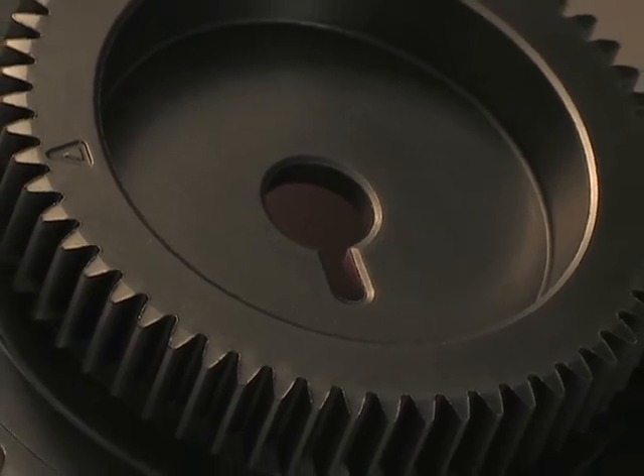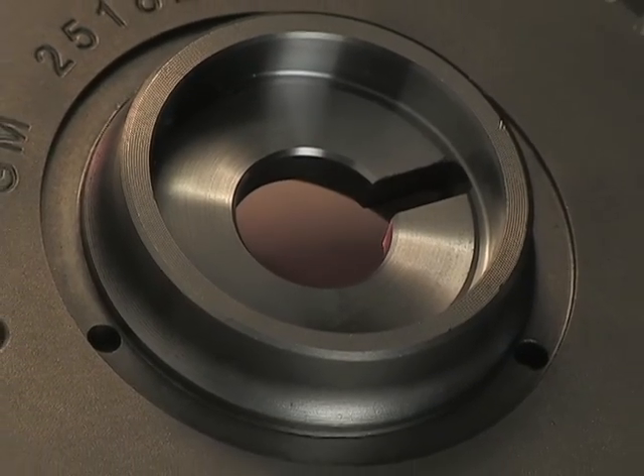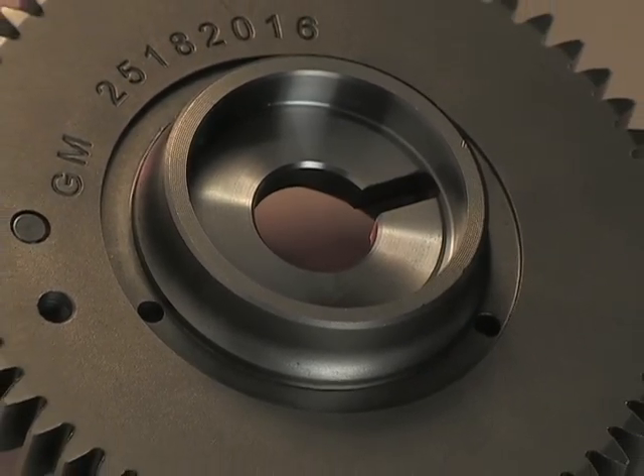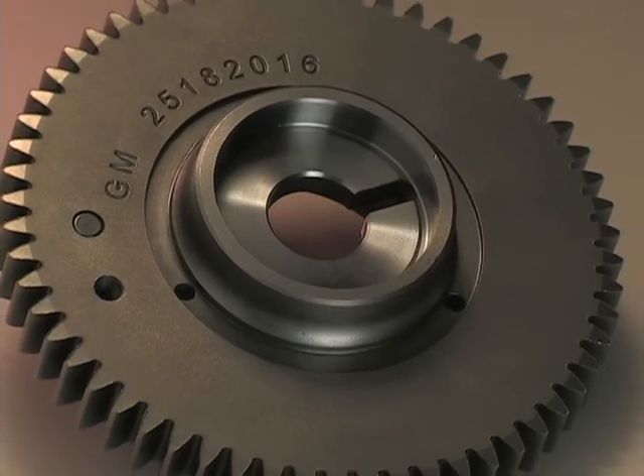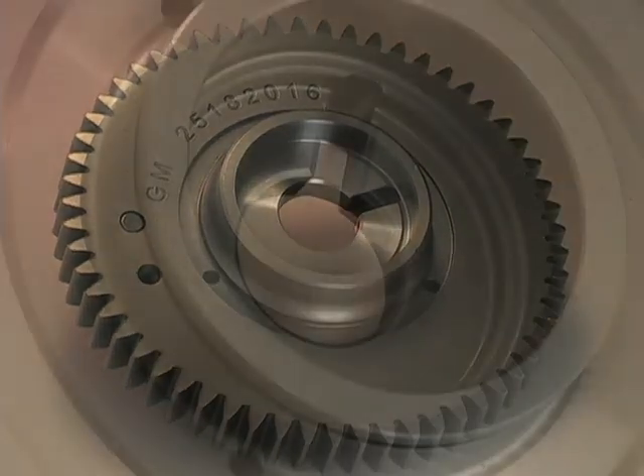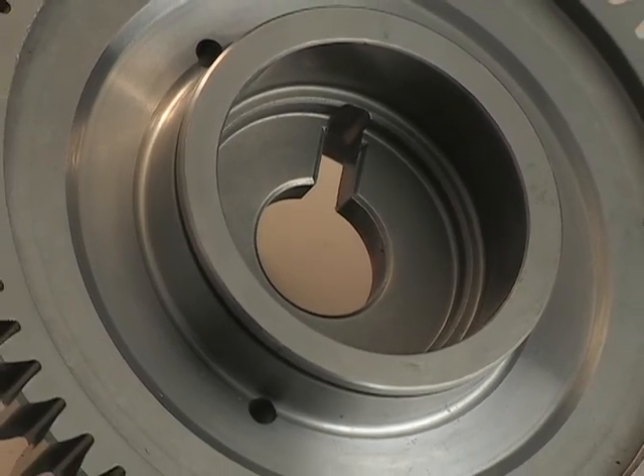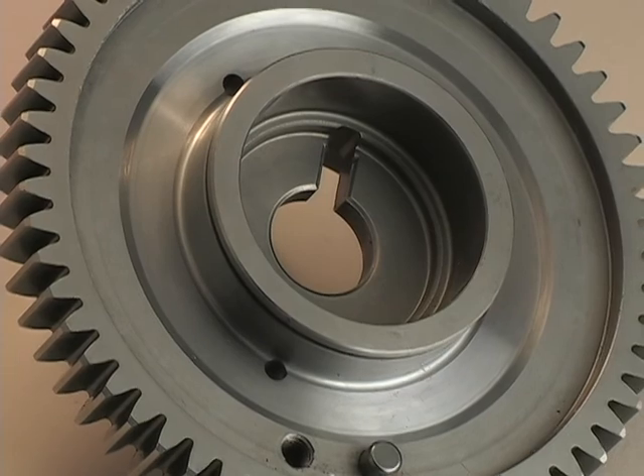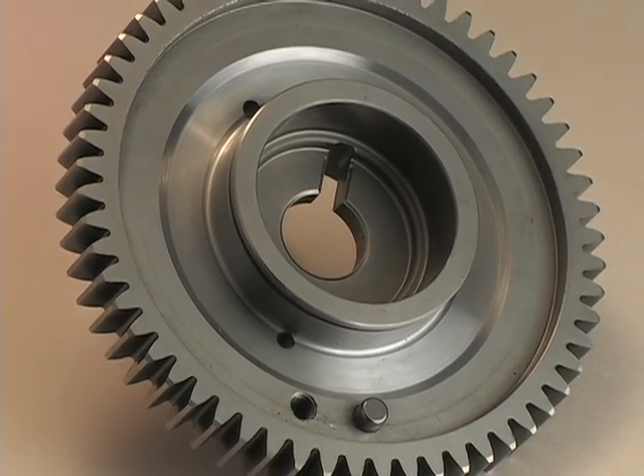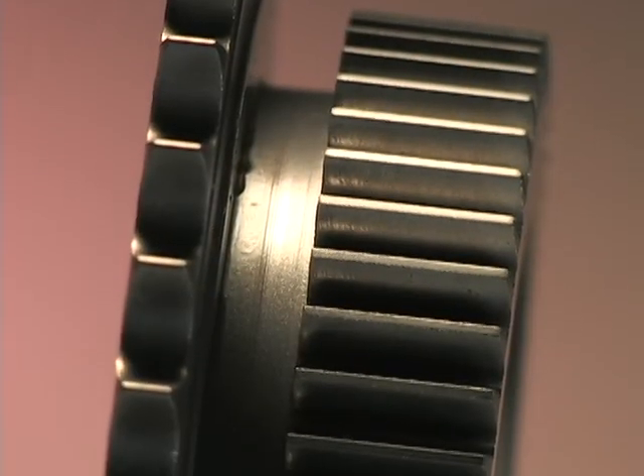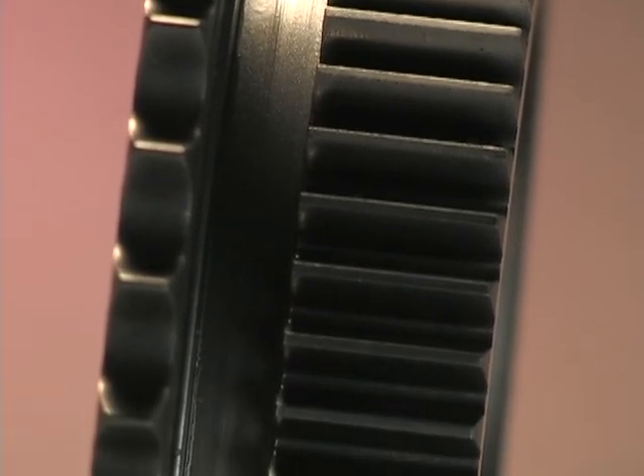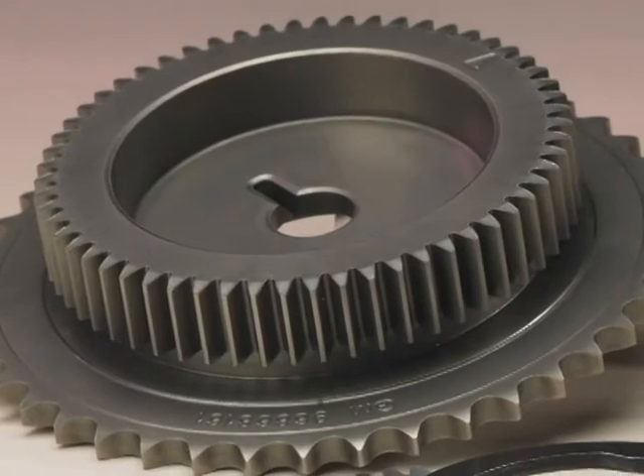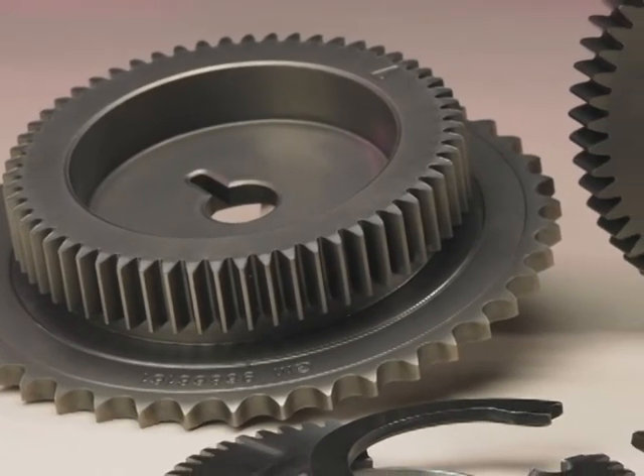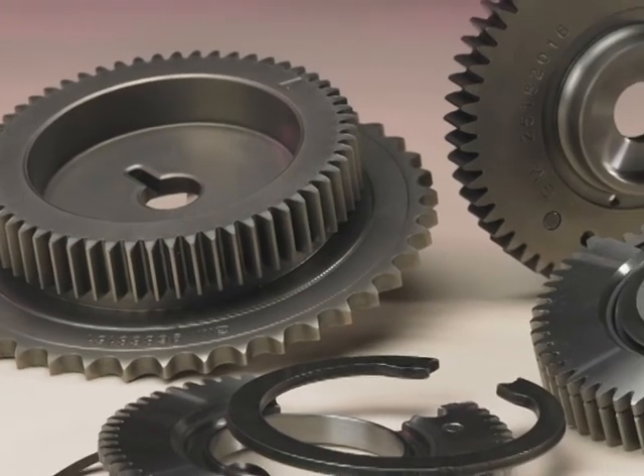noise, vibration, and harshness. Warm compacted to a 7.2 grams per cubic centimeter minimum density on the teeth, the PM steel gears have an ultimate tensile strength of 196,000 psi, typical yield strength of 161,000 psi, a fatigue limit of 55,000 psi, and 74 HRA hardness after carburizing. The gear teeth are shaved to achieve an AGMA 9 rating. PM's highly efficient material utilization clearly demonstrates its sustainability benefits here. The more traditional fabrication method for diesel engine parts, machined wrought steel gears, would have required 8.5 pounds of additional material to be machined away.